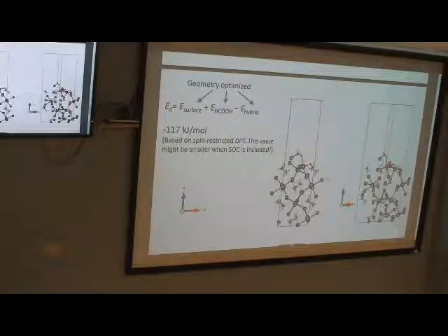There is a very big human influence in how you construct initial geometries. If you do something wrong, it probably will correct you, but not always. So what's the conclusion? We need to screen several initial guesses, several initial binding geometries, and select which of them are chemically more stable on one hand, and which of them give binding energies in reasonable agreement with experiment. So there are 2 criteria. So can you figure out if it dissociates somehow or not? Or whether these are all molecular adsorption geometries? So far, well, this is kind of a dissociated geometry.